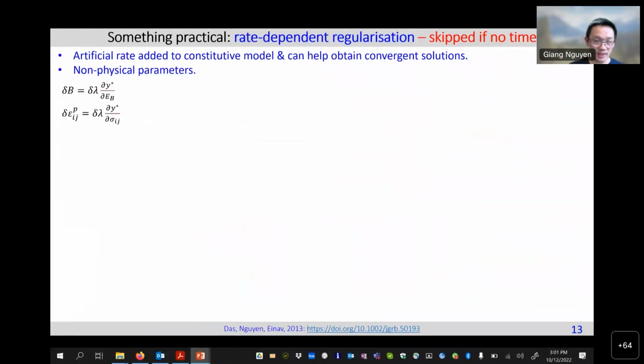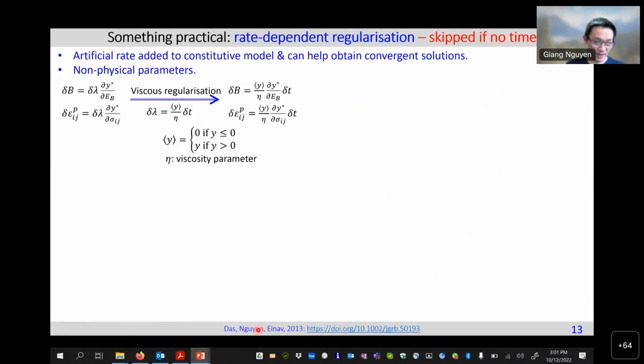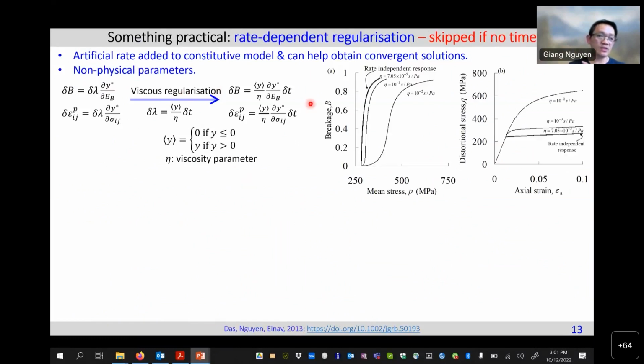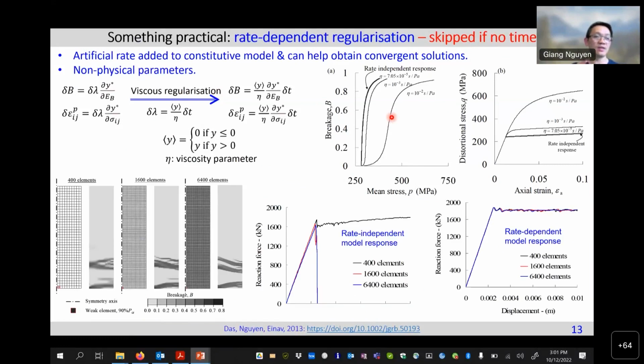So the last thing here that we did with Professor Das at Sydney and Professor Aina is to add some artificial viscosity to make a rate-independent model behave like a rate-dependent one, so that it is sensitive to the rate of loading. This is artificial. It has very little physics there, but it's useful. It makes things work nicely with a minimal amount of time in the implementation. We did something here to prove that without rate dependency, with different meshes, nothing will work. No convergence as you would expect from finite element analysis, but with rate dependency added, we managed to get something useful, although what we're doing here is artificial. So that's the issue.